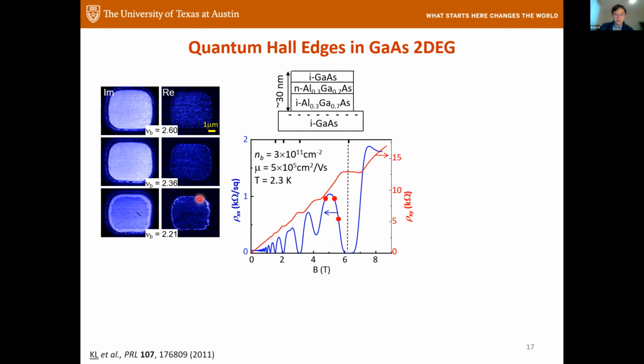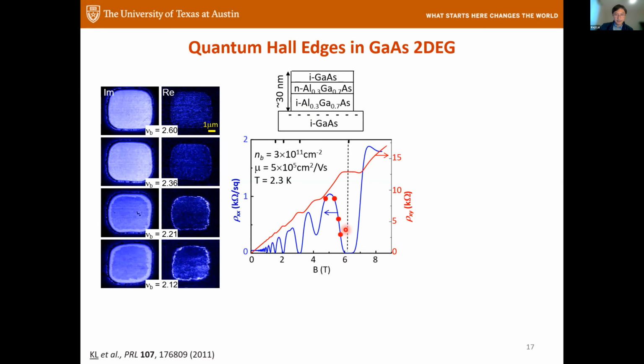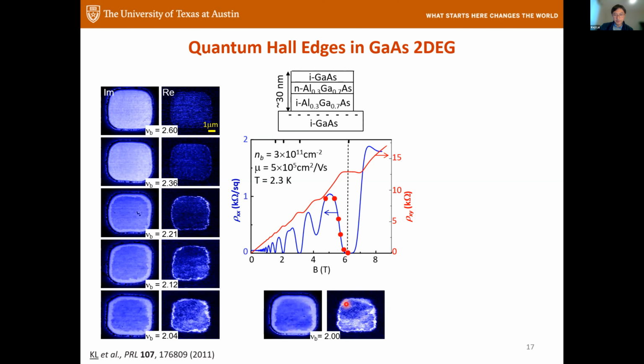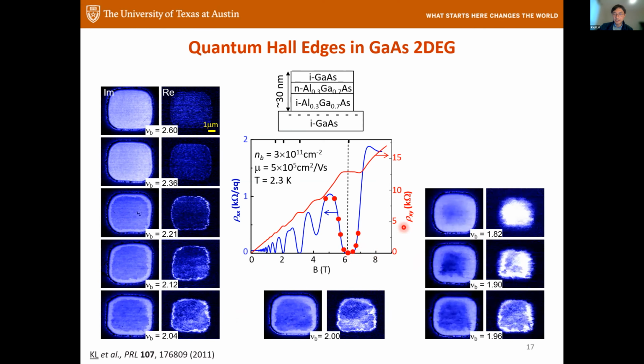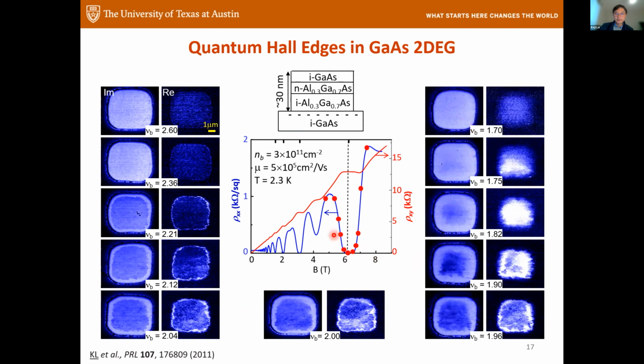And I'm sure everybody can start to see there's a ring that's higher signal, and a ring here which is lossy. Then this feature gets stronger and stronger, and the material becomes very lossy in the middle of the quantum Hall system. And then eventually it goes up and disappears. I need to say that this is in kilo ohm scale. If you convert it to ohm scale, this does not go to 0. So this temperature is not low enough for us to see completely 0. Hopefully that explains this.